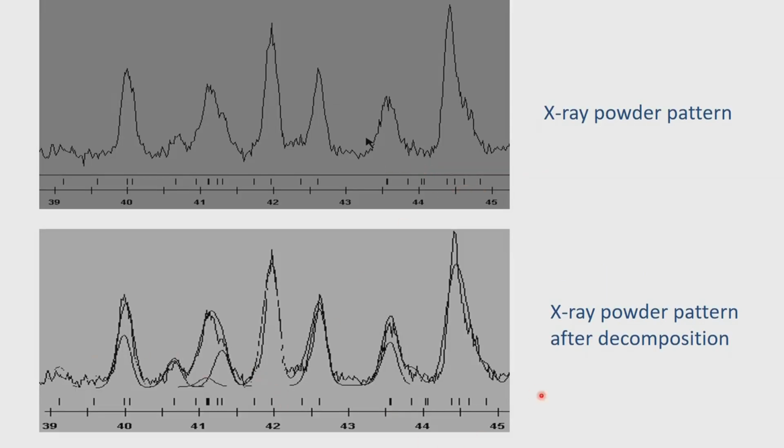Let me take you back here to show what I mean by that. If you look at the count of peaks 1, 2, 3, 4, 5, 6, 7, in this case there were 7 peaks on the powder pattern. But if you look down here and count the number of reflections that are possible, you will see 1, 2, 3, 4, 5, 6, 7, overlapped peak, 8, 9, 10, 11, 12, 13, overlap peak, 14, 15, 16, 17. So, you have a very significantly larger number than what you have there. And of course, the overlap peaks will remain overlap. So, we have to do the pattern decomposition to identify individual ones, and we have done that through profile analysis.